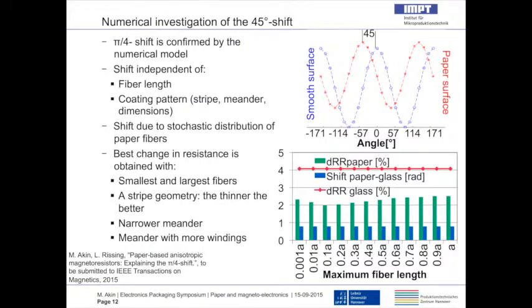What we have obtained with the simulations is this graph here on the top right side. The blue curve is the magneto-resistance of the permalloy coating on a smooth surface. The red curve is the magneto-resistance of the coating on a paper surface. And if you look at the shift from peak to peak of the blue curve to the red curve, it is a 45-degree angle. This is happening in the simulations where mechanical properties are not modeled and local magnetic fields are not modeled, basically just a homogeneous magnetic field and electrical resistance as a function of the network topology of paper, even a really smooth paper.